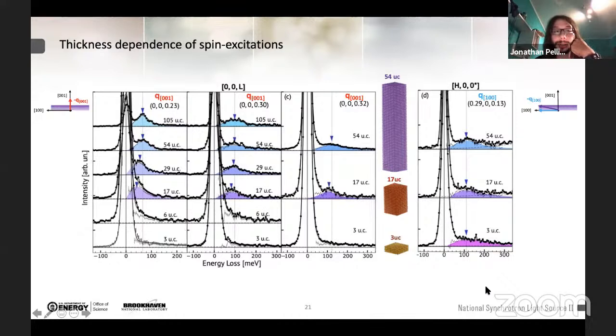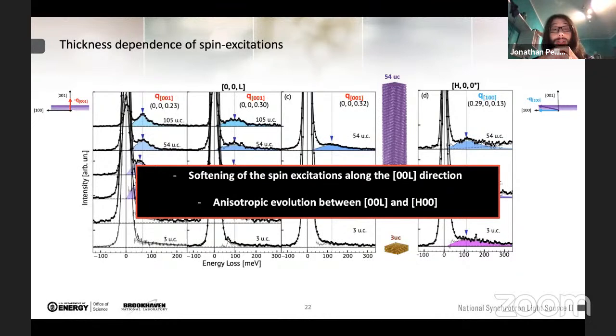So this brings two observations. One is the softening of the spin excitations along the 00L direction as we decrease the thickness. The second is that, based on the thickness, we have an anisotropic evolution between in-plane and out-of-plane directions.